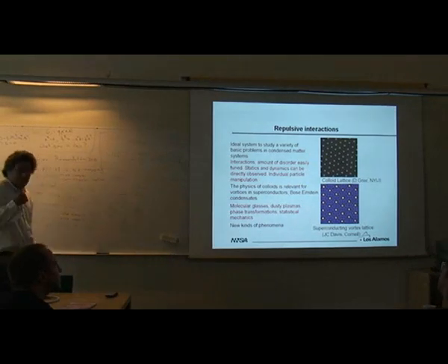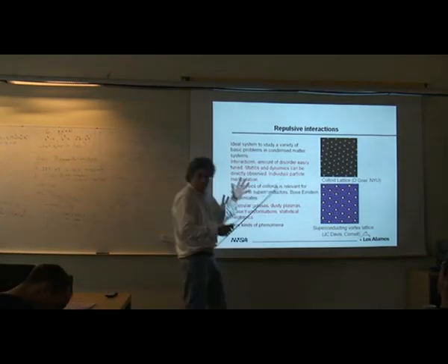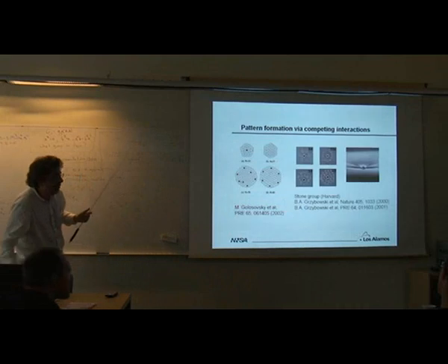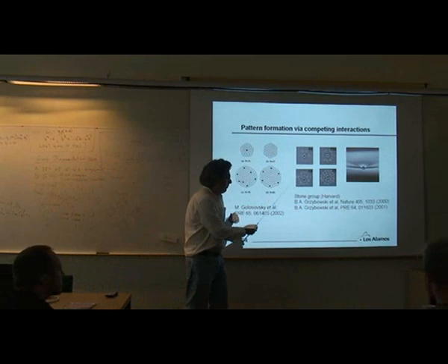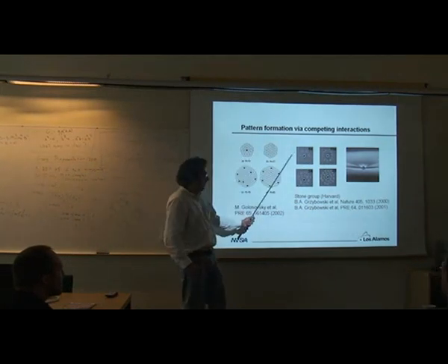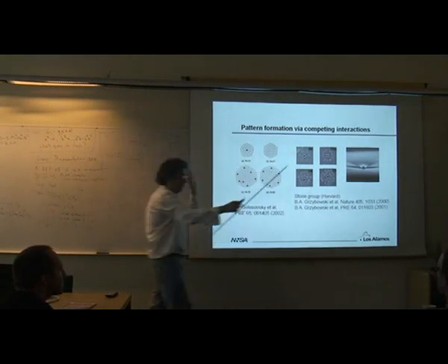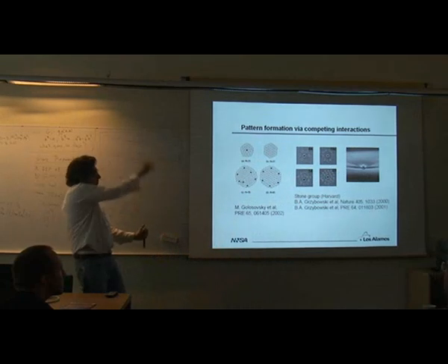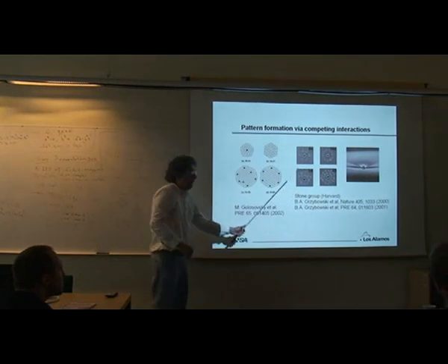So you can also make systems, particularly soft matter systems, where you can tailor the interactions, where you have, say, some screened charge, so that means it's going to certainly be repulsive on short range, but you can have some long range attraction. And here's an example of a system with some particles that are charged. They're on a water-oil interface, such that they cause a divot in the surface, which creates this long-range stress field. And ideally, if you have another particle here with this divot, by coming together and sharing the divot, that's less energy than having two divots apart.